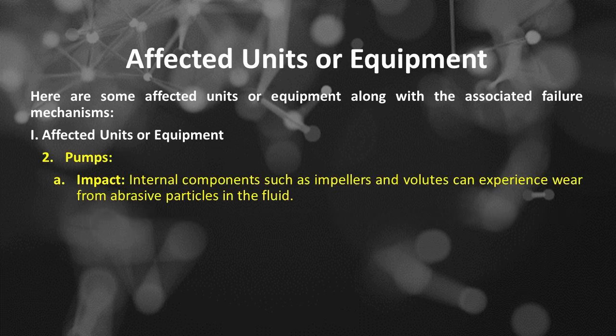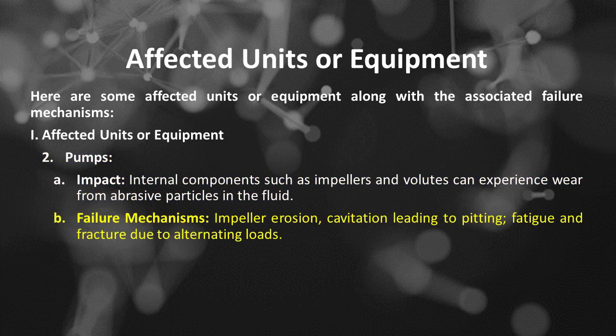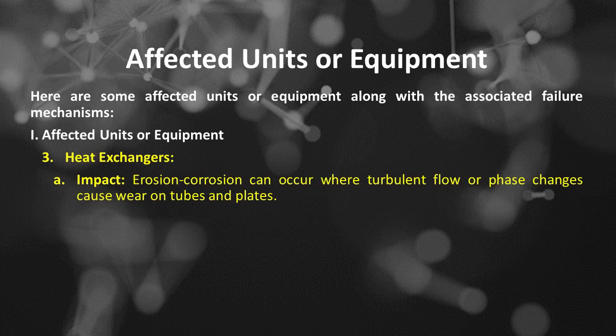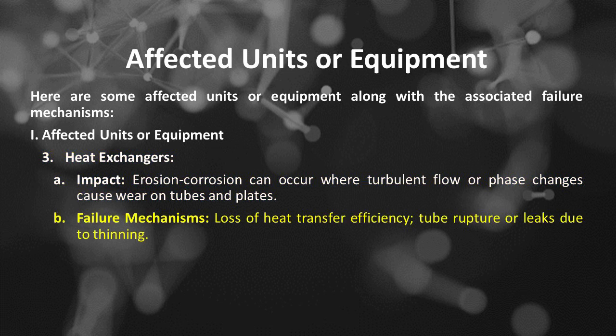Number 2 of affected units or equipment is pumps. The first is impact: internal components such as impellers and volutes can experience wear from abrasive particles in the fluid. The second is failure mechanisms: impeller erosion, cavitation leading to pitting, fatigue and fracture due to alternating loads. Number 3 is heat exchangers. The first is impact: erosion-corrosion can occur where turbulent flow or phase changes cause wear on tubes and plates. The second is failure mechanisms: loss of heat transfer efficiency, tube rupture, or leaks due to thinning.